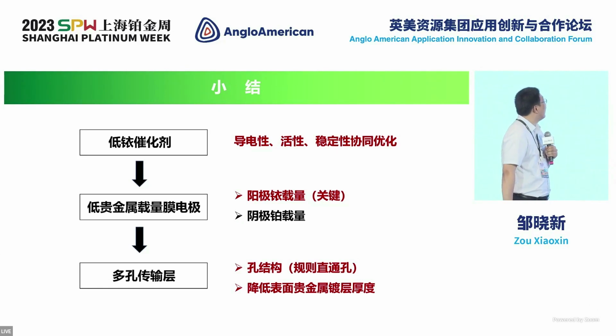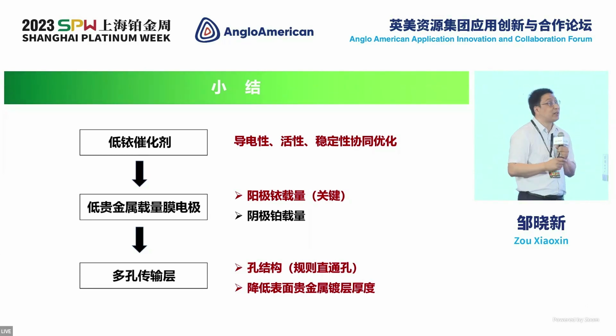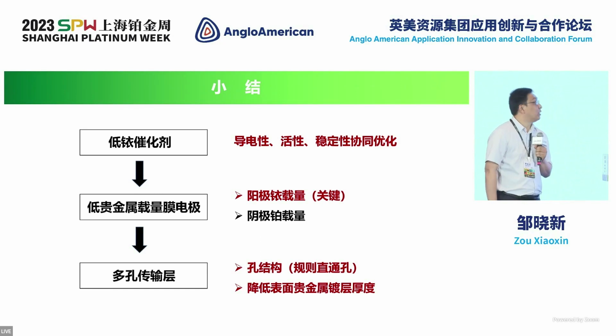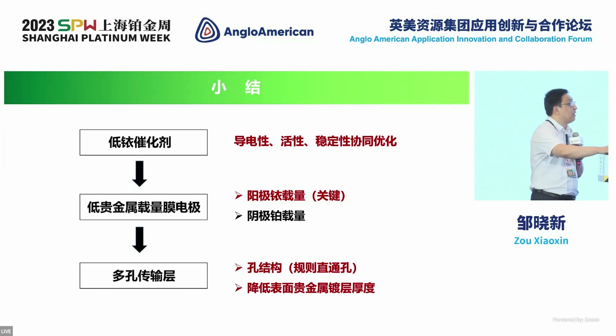And the second is anode iridium loading technology in order to turn it into low loadings of noble metal. And the loading on the part of anode is key because on the part of cathode, we have already reached the ceiling, 0.2, 0.3 milligram per square centimeter. However, in China, at the anode level, mostly are above 2 milligram, and sometimes the figures are as high as 3, 4, or even 5 milligram. So there's a lot of things we can do and need to do.